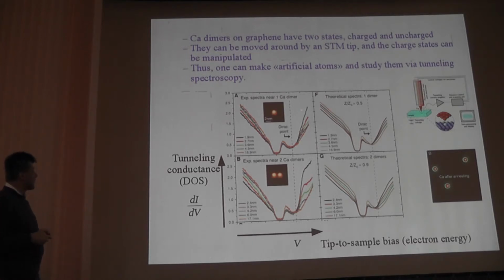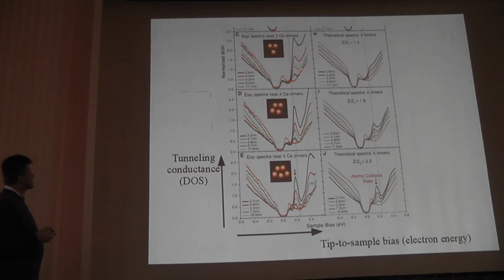And so you can probe the behavior of electrons in the vicinity of such a dimer by measuring the tunneling density of states. If you just take one dimer, the density of states isn't much different from the one without a dimer. It changes with two dimers. Then, if you add three dimers, you can see that a peak is growing on this density of states. You put four dimers, the peak is higher and higher, and also moves in energy. So this peak can be identified with the atomic collapse state.